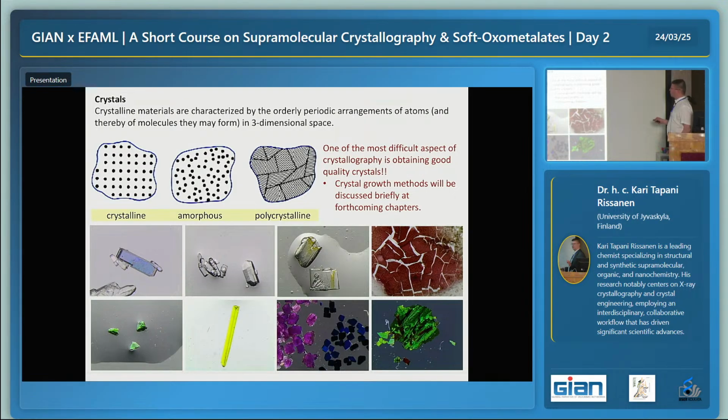And now in here, there's 1, 2, 3, 4, 5, 6, 7, 8, 9, 10, 11, 12. In this polycrystalline single object, there are actually 12 single crystals. In theory, we can use these kinds of materials also, but in practical terms only when we have 2 of them. And then we call it a twin crystal. Twin means a double crystal, but it's physically one object. You cannot see by eye that it actually consists of 2 crystals. Only the X-rays, only the diffraction can tell you this, but that's the idea.